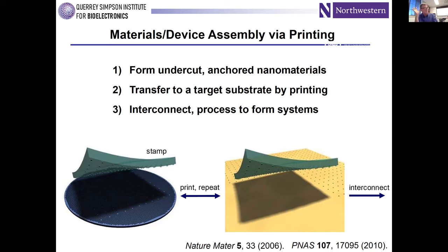So as you peel the stamp back, you fracture the anchors. The semiconductor material is now inked onto the surface of the stamp. You just index the stamp over to a target surface. Could be a sheet of plastic, could be a plate of glass, could be a slab of rubber. And then just in a contact process, you print out arrays of these tiny elements of materials. And so the trick here from a physics standpoint is, how do I switch the adhesion strength from strong to weak to allow high efficiency inking and printing with a stamp material? And there are a variety of ways to do that. I won't get into the details, but this can work at spectacularly high levels of efficiency, positioning accuracy, and throughput as well.